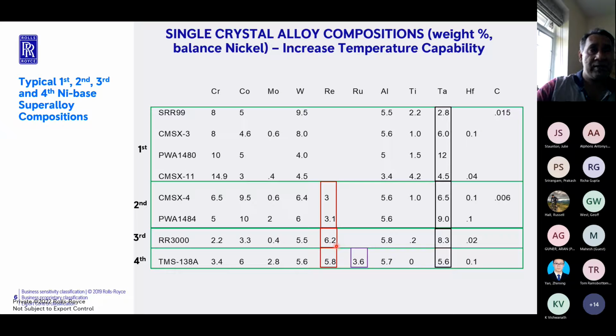The other problem with third generation alloys is they're poorer in oxidation compared to second generation alloys. So clearly you need to coat them. But one of the ways of overcoming the drawback of them being unstable is by lowering the amount of chromium. So if you look at third generation nickel-based alloys, whilst they have higher rhenium, they generally will have lower chromium. The lower chromium is done primarily because you want to not lose the strength of this alloy over a protracted period of time because of these TCP phases. But the moment you decrease the amount of chromium, you simultaneously decrease the corrosion resistance and the oxidation resistance. So generally speaking, third generation alloys are poorer in oxidation resistance compared to second generation alloys.